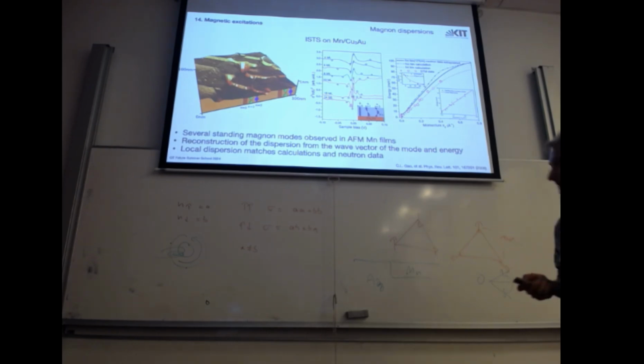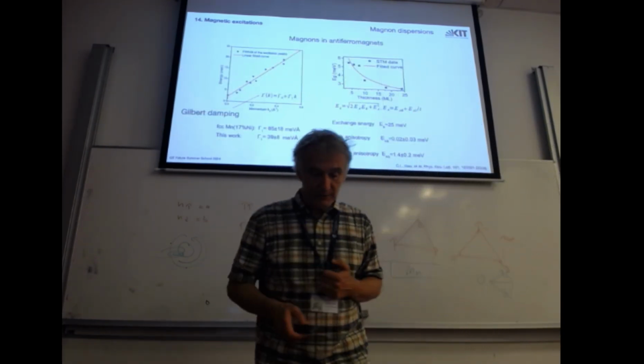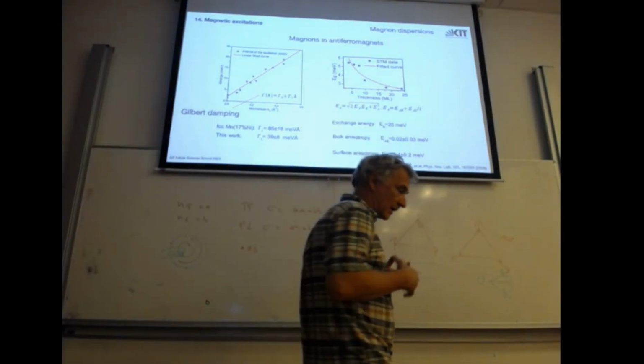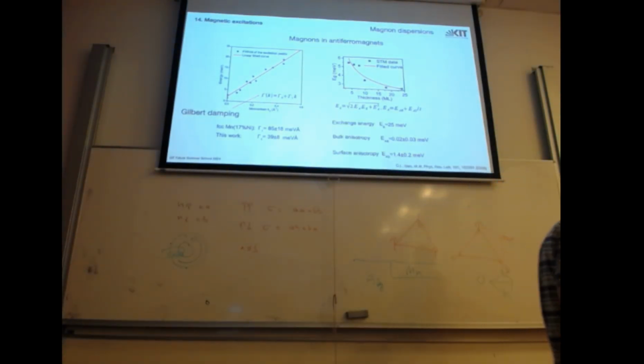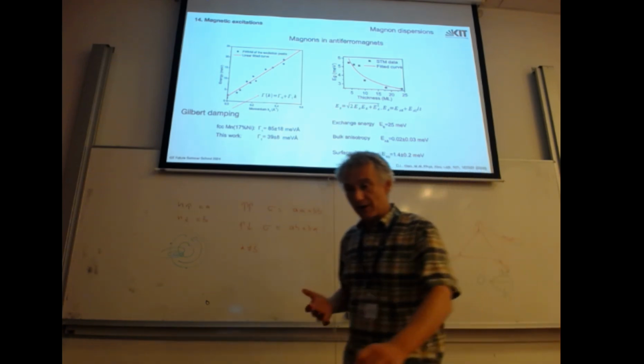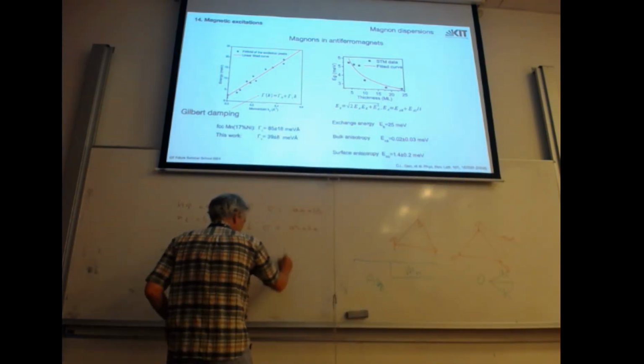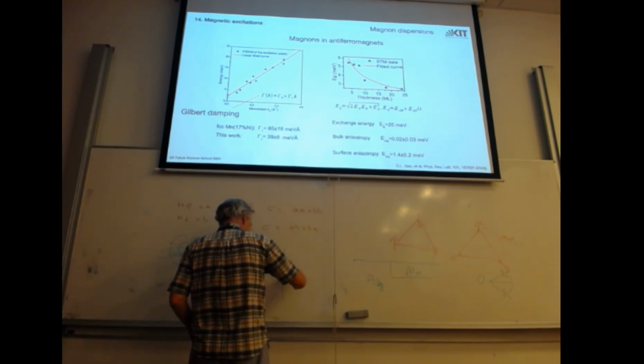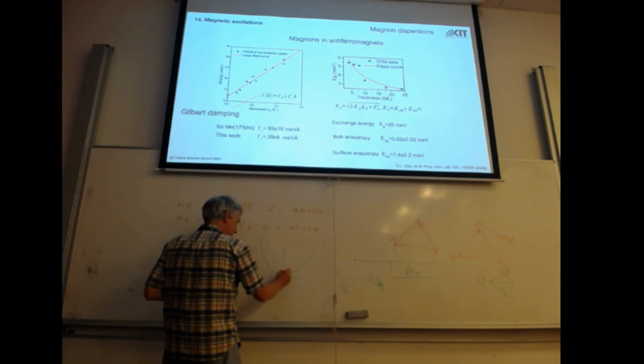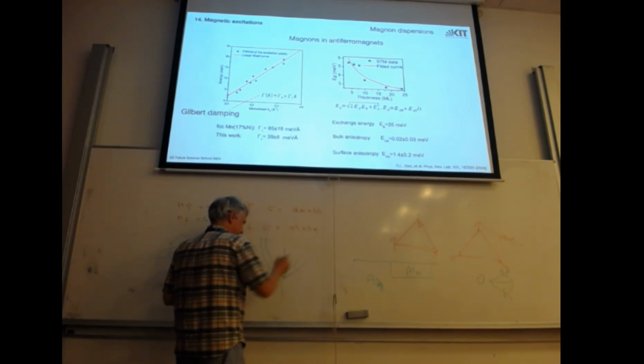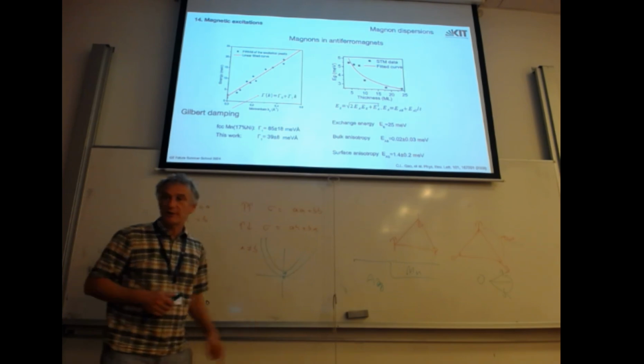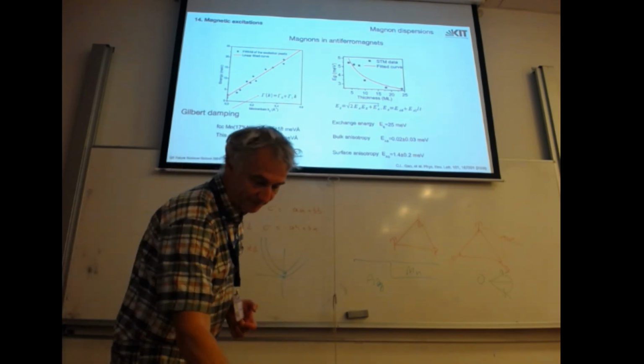Why is that? So as you know, in ferromagnets, the Q equals 0 magnon is a coherent rotation of the magnetization, and it costs maybe anisotropy energy. So there is a spin splitting gap. So the normal magnon spectrum without spin orbit coupling goes to 0. This is now a ferromagnet, 0, and with spin orbit coupling. The energy I need to rotate the spin.